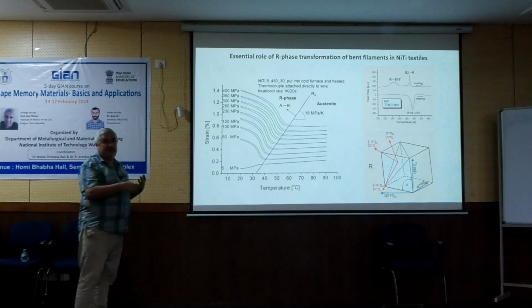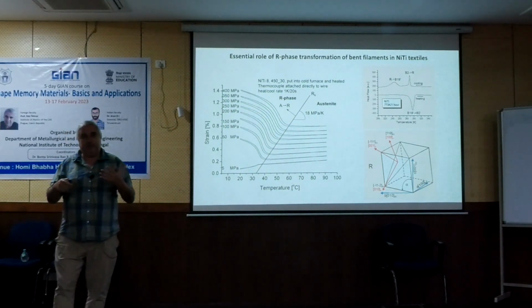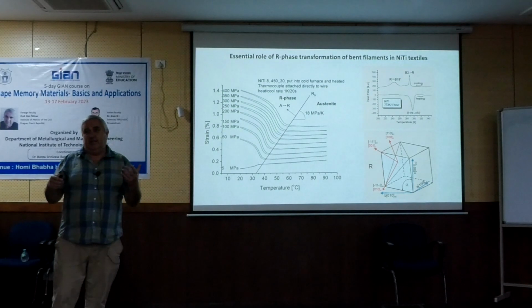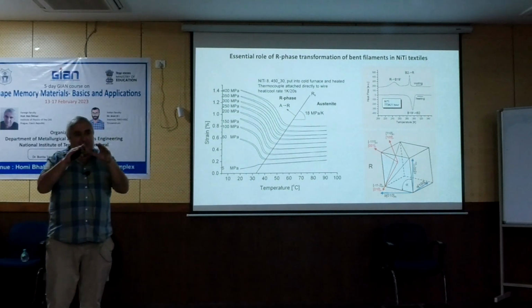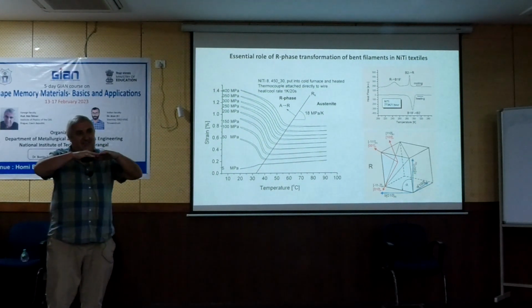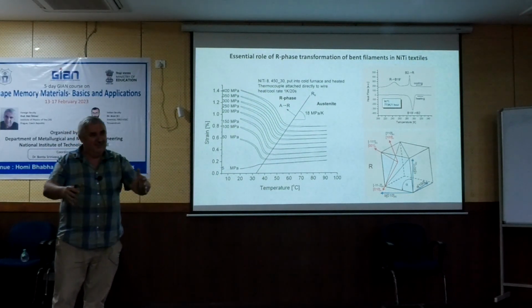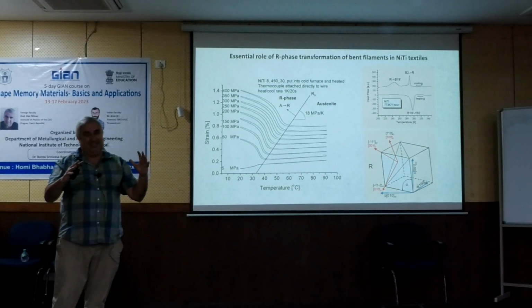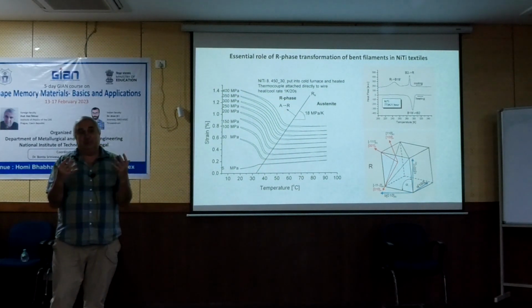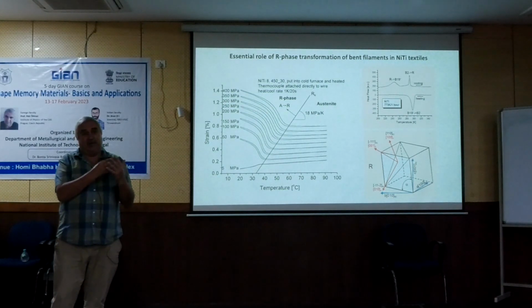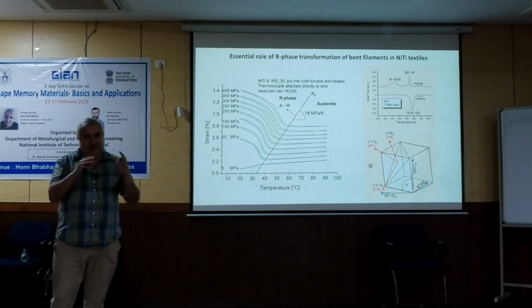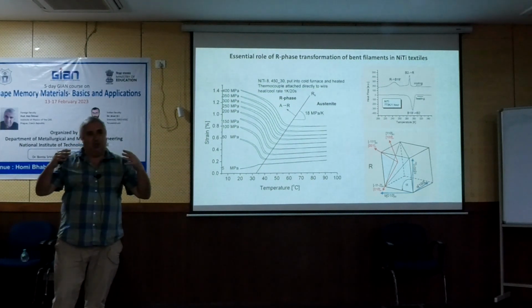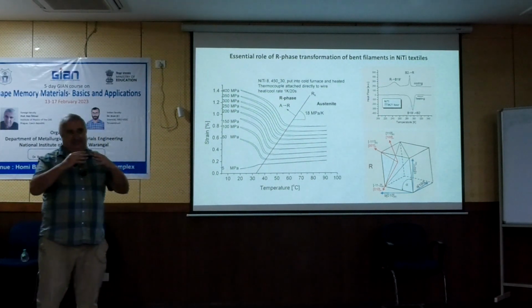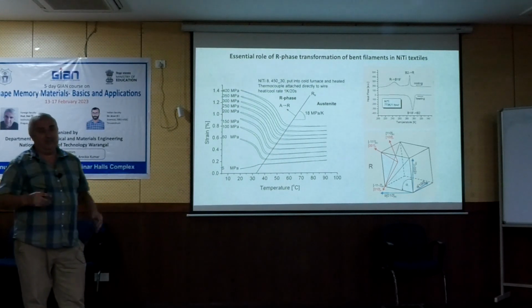R-phase is extremely useful in these textiles, because if it's made from R-phase wire, the R-phase gives only this 1% strain, but if you imagine this 1% strain embedded in a textile, it becomes really very flexible, but put the current through it, and it becomes stiff very quickly. So you can use this R-phase transformation to change the flexible textile to a stiff textile. I mean, not so much that you can fly on it, but definitely in a very interesting way.